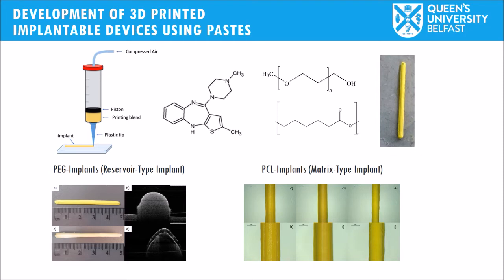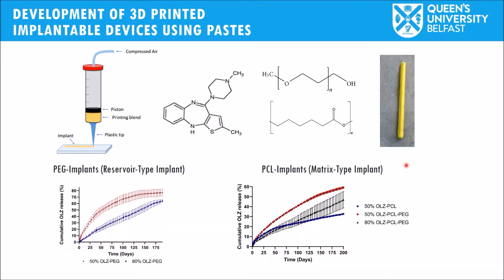And if the residual levels are controlled, there is no problem. So basically what we can see in the reservoir type implants is a sustained delivery of olanzapine for around 200 days. We have 2 drug loadings. You can see that the drug loading influences the release in the reservoir type implants.